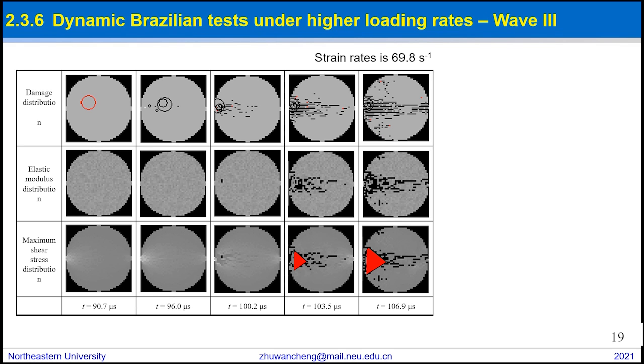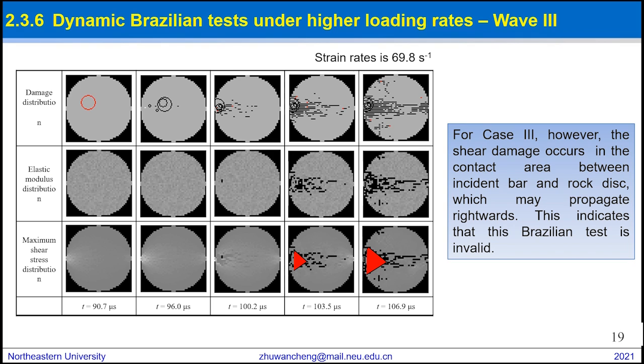Under the impact of wave 3, as shown in the figure, although the tensile damage still initiates near the horizontal diameter, the damage in shear mode, shown as white color, accumulates in the contact area between the incident bar and rock disc, which may propagate rightwards until the contact area between the rock disc and transmission bar.